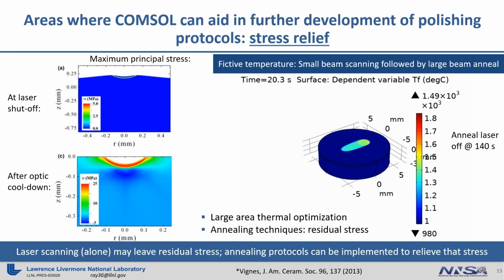And on the video here, in the beginning of the video, you'll see the laser scan across the surface, and you'll see the residual fictive temperature. That's what's plotted, fictive temperature. And then a little bit later, there's a large beam laser that's annealing. If you're going to use a laser to polish your optics, you would probably rather use a laser to anneal your optics. It's simpler. You can use it in the same setup. It could be much, much faster, like hours, days faster. And so there's a lot of advantages for using an annealing laser.